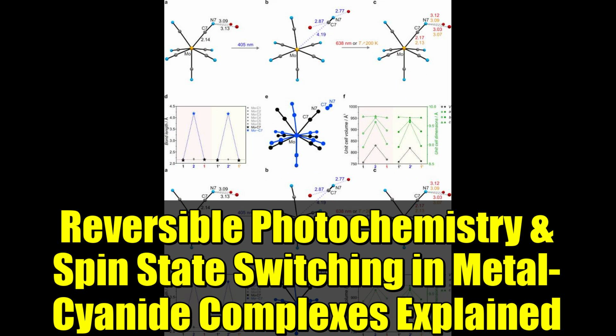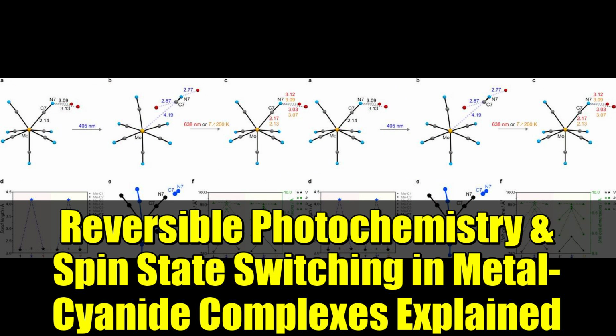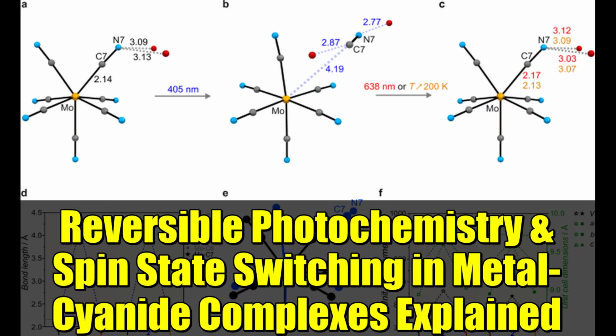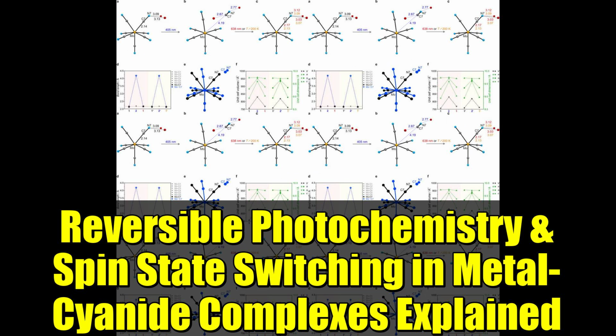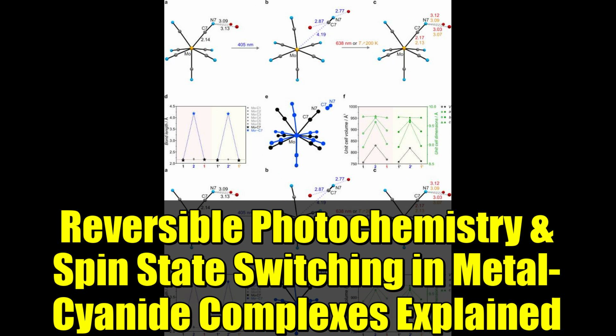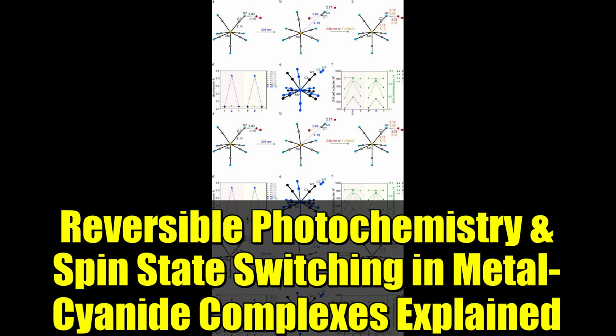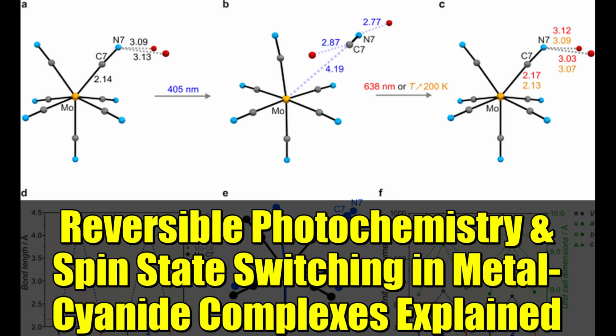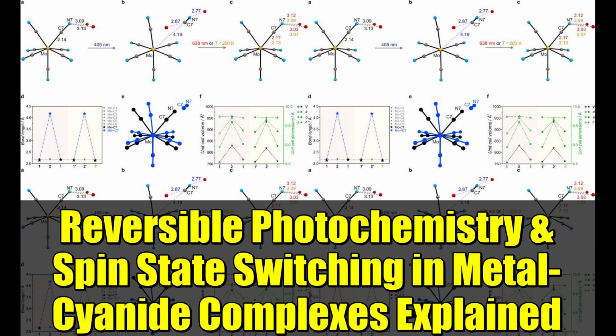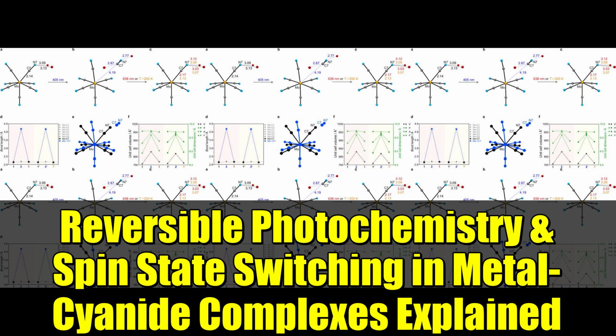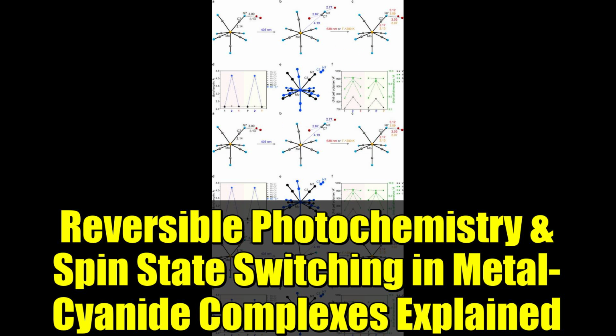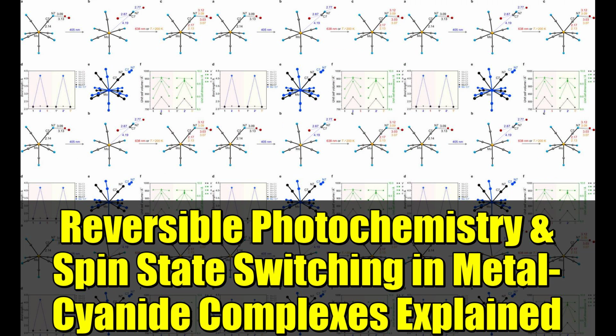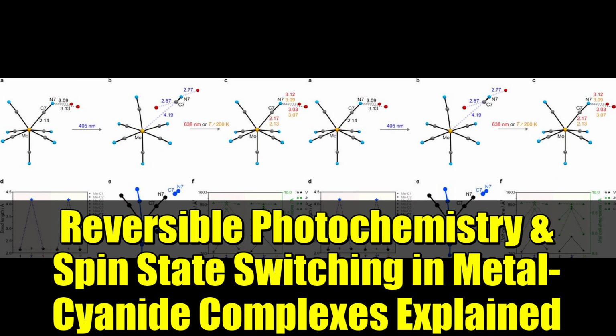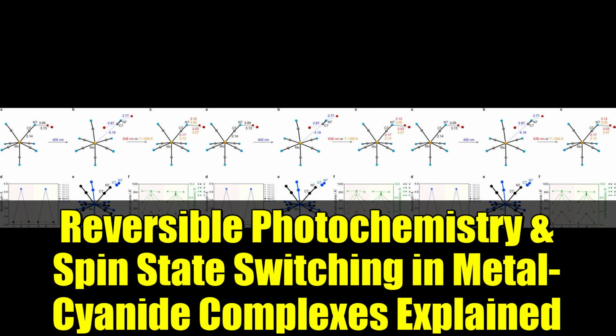4,770 ± 90 K. Hence, with increasing temperature, high-energy states become populated, enabling 2 to overcome the energy barrier of cyanide reassociation and relaxation to 1. The relaxation behavior of 2 is comparable with that reported for the record-holding photomagnetic molecular Prussian blue analog, Co4Fe4. Importantly, the substantial energy barrier of the thermally activated metal-cyanide association 2-to-1 does not prevent this process from happening under 638 nm irradiation at low temperatures, as demonstrated by SCXRD at 30 K or optical reflectivity